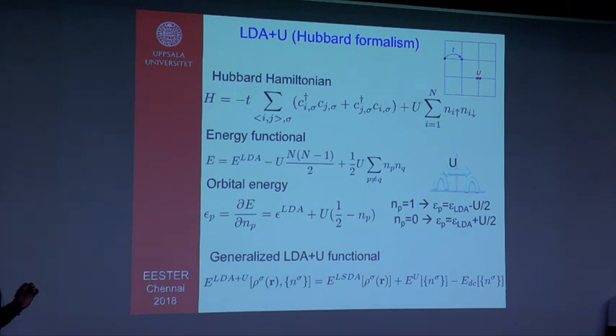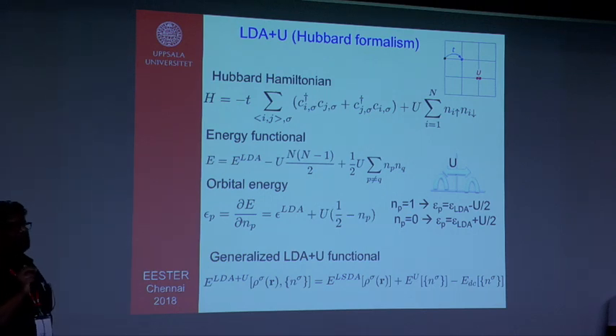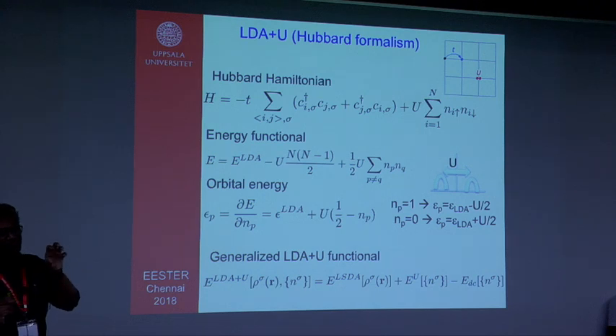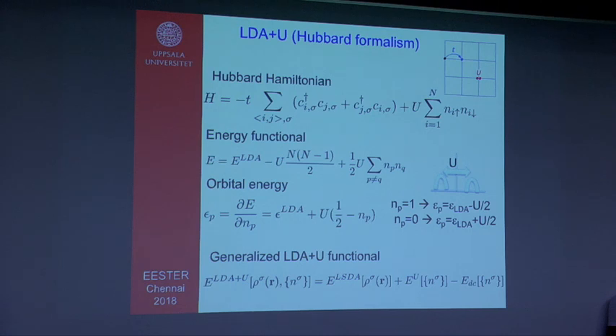Now I just want to say that these corrections that you do are done only in the correlated subspace, not for all orbitals, but for the correlated orbitals only. So it gives us a little bit of a problem, because we don't explicitly change the sp states in this. We only do the corrections in the d orbital subspace or f orbital subspace, and due to hybridizations, the other states might move a little bit, but we are not doing corrections for all the states, which is different from hybrid functionals, where we correct all the states, or even GW, where you take into account all the states. Here it is done in a correlated subspace only.